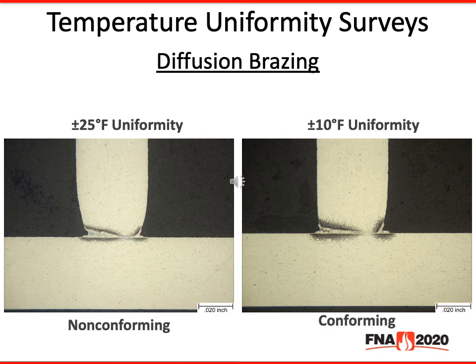As you can see in the matrix, the eutectic is diffusing into the material, which is the darkish black-gray shading. In between that, you can see the solid solution loops growing on the plus or minus 10 uniformity, where on the plus or minus 25, they're not as prominent, and you can see more of a eutectic matrix still in the joint.